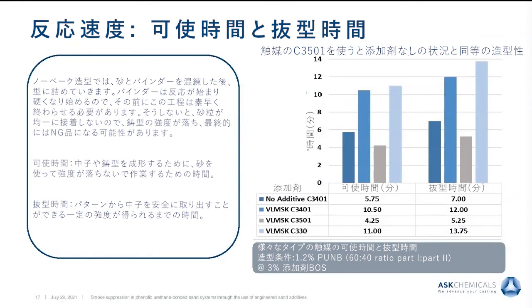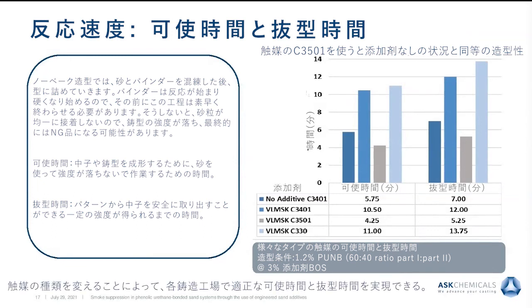So when we put the additive in, and this is what we expected, we were going to slow down the work time. But again, we just adjusted the catalyst to bring this back. And actually, it was interesting because we didn't change the percentage of the catalyst, and we were able to actually speed up the work time a little bit. So that means we could probably use 2% of this catalyst and get back to where the no additive conditions are. Again, there are some catalysts that we found not very helpful in this case, like the 330, which didn't really help here. And the same applies for the strip time, they're kind of correlated. So if you can adjust the work time with a different catalyst, it's going to work for your strip time.